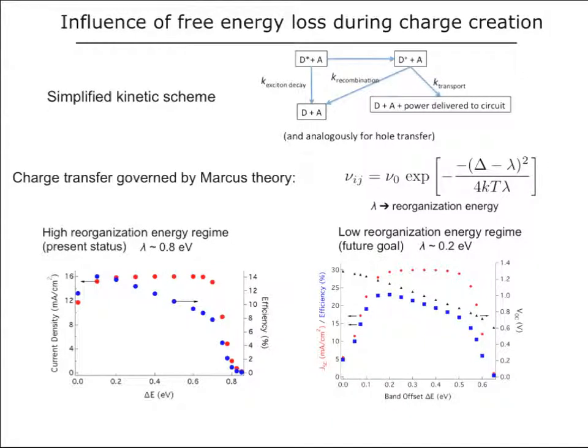So what we can do is go back to our kinetic scheme and draw a simplified version where we remove this charge transfer state business for a little bit and just consider where we have an excited state donor and an acceptor, which we can go through to create free charges, or we have a ground state where we lose energy. So if we apply the standard charge transfer theory, and that standard theory is Marcus theory, which is developed for electrochemical charge transfer reactions, but we think it's valid in this case as well, then the critical component is the reorganization energy. That is, when you move a charge from one molecule to another, what is the energetic change in the distortion of all the bonds?